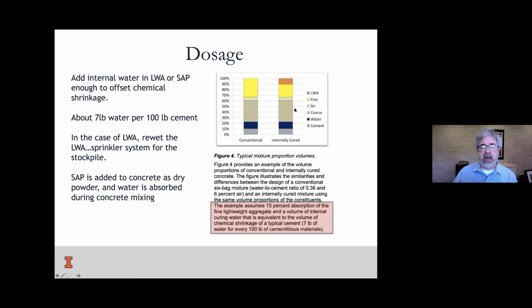And so we talked about what that chemical shrinkage is. We know it's 6 or 7% by volume of the cement. And that comes, in this case, I'm summarizing it as 7 pounds of water per 100 pounds of cement as a rule of thumb. In the case of lightweight aggregate, you want to make sure that you're using saturated lightweight aggregate. If it's dry, it's not helping you too much, or it won't work the problem as effectively as bringing it in as a saturated particle.